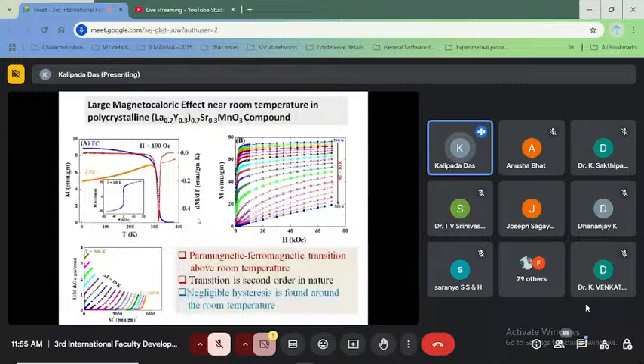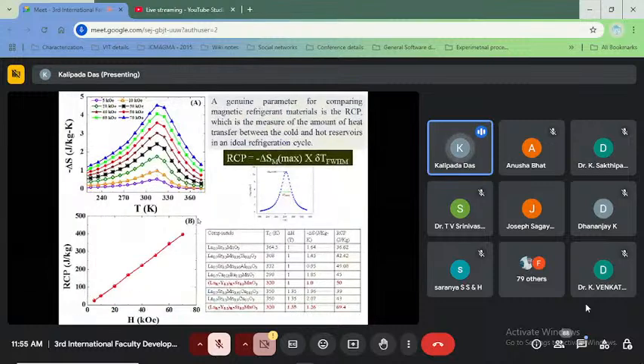And we have studied the magnetocaloric effect, and we see a large magnetocaloric effect as well as a large relative cooling power. Relative cooling power is nothing but, suppose you have the magnetocaloric entropy change versus temperature curve, its maximum value multiplied by its delta T FWHM, that means the full width at half maximum. The product of these two terms is the relative cooling power. So it is also a genuine parameter for practical utilization of the material.